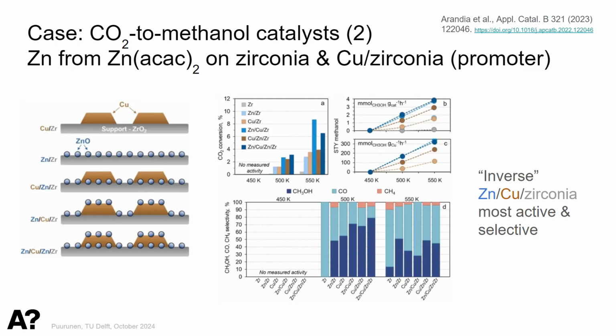Also, we had the least methane selectivity. So you would want to selectively make methanol, but you can also make CO and methane. And those had also the best selectivity. So of this tested series, we concluded that the so-called inverse catalysts, where you first had the copper and then zinc on top, were the most active and selective. We have continued this series, but we have no publications of it yet, trying also different supports, but we have actually not been able to find a better one than this zirconia.